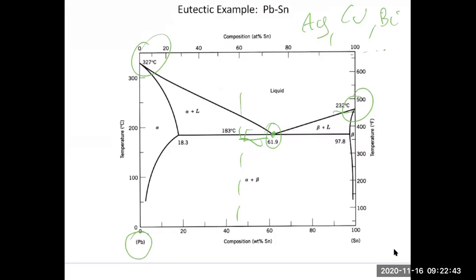Plumbing solder is different, because when you do plumbing, you solder the joint and you want to be able to twist it. So there's something they call the mushy zone, which is when you cool through the two-phase region. So in plumber solder, you don't always want instant onset of solidification. You actually don't want to be in the eutectic. But the main reason is really cost, okay?